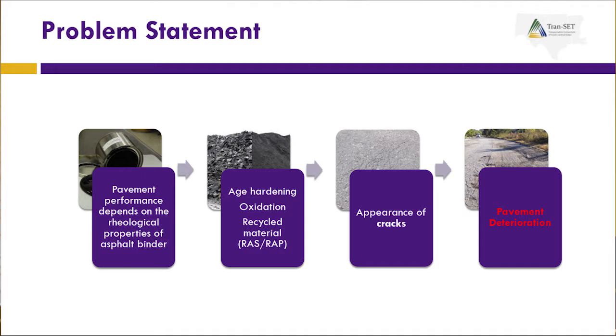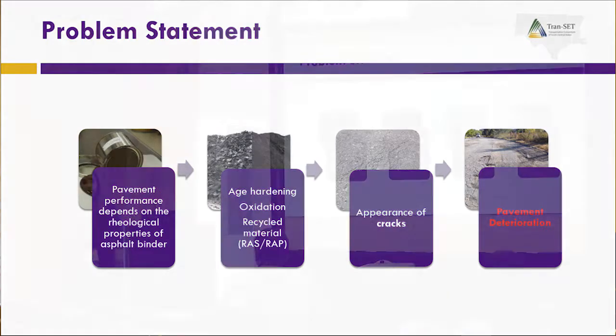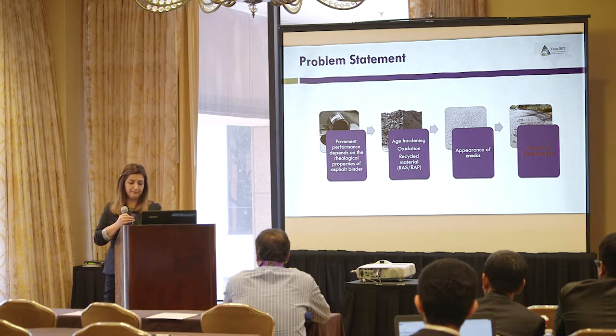But the problem is the asphalt binder in recycled material has been subjected to severe oxidation during its service life. So the binder is hardened, brittle, and if we use it in construction of new pavement, it can cause increased crack susceptibility, and eventually it can lead to deterioration of the pavement.